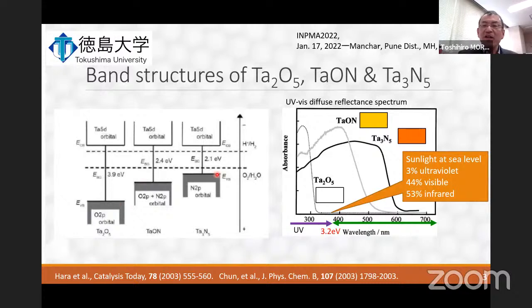Usually, nitrogen 2p orbitals have higher potential energy than oxygen 2p. So the increase in nitrogen content in oxynitride or nitride materials results in a higher negative potential of the valence band compared to that of tantalum oxide, and narrows the band gap. The band gap positions of both tantalum oxide and tantalum nitride are shown. Tantalum nitride can be used for the photocatalytic water redox reaction, since both materials possess band gap energies within visible light energies, from 380 nanometers to around 700 nanometers. So these materials are colored yellowish orange or reddish orange, respectively.